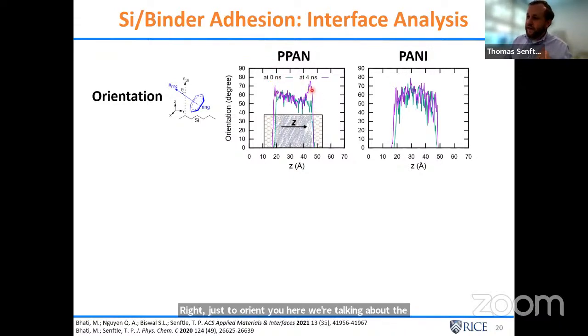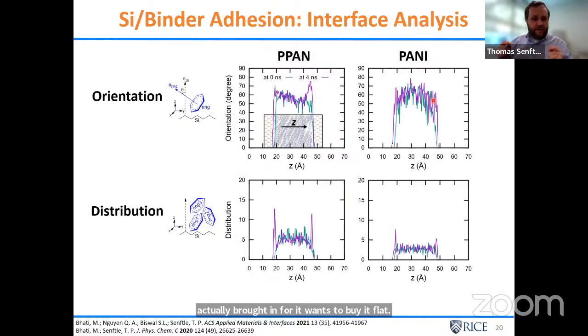We see that this angle really starts to go to 90 degrees towards the interface, and that is reflecting the p-pan's tendency to bind straight up and down to form this vertical. That doesn't happen with the polyaniline. The polyaniline actually broadens, right? It wants to bind flat. So this matters if we start to count how many chains are bound to the surface, right?